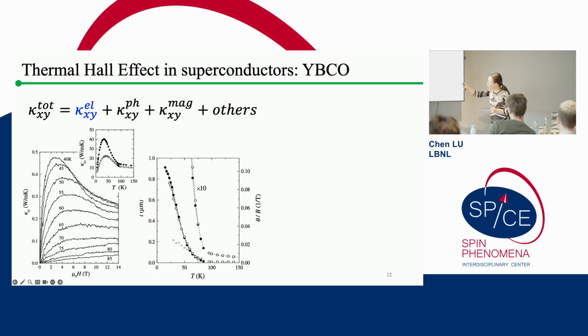This is exactly why, in the thermal conductivity and thermal Hall conductivity, you still see a very big signal when the temperature is below TC. So what happens here is you see the thermal conductivity and also the thermal Hall conductivity dramatically increase when the temperature goes below TC. It is because below TC, electrons form Cooper pairs, which means electron-electron scattering becomes smaller, which greatly increases the so-called mean free path of the electron, which is what I plotted for you on the right-hand side. So this strong increase in the mean free path of electrons gave you all this strong signal coming from both thermal conductivity and thermal Hall conductivity. So the conclusion here is